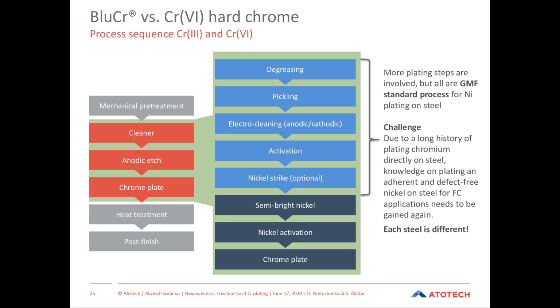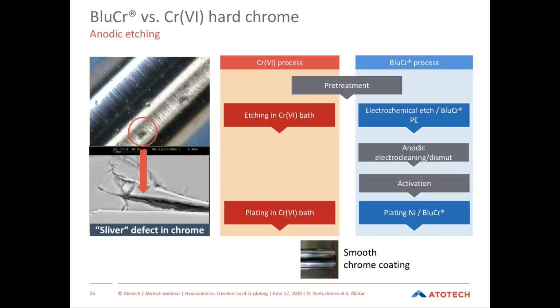This is because the base material is mostly steel, but not every steel is the same, and depending on the steel, if it's a higher alloyed steel, maybe you will need a nickel strike in between to achieve good adhesion. So, also an important point is to mention some words about anodic etching.